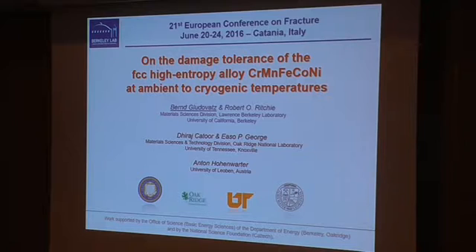The highest degree of work hardening also obviously occurred at the lowest temperatures, which is obvious from the difference here between tensile and yield strength. The yield strength approximately doubles from room temperature down to liquid nitrogen temperature, which is probably associated with thermally activated yielding. For such a thermally activated yielding process, however, it's somewhat unusual that there was no sensitivity to strain rate changes, as we can see here.